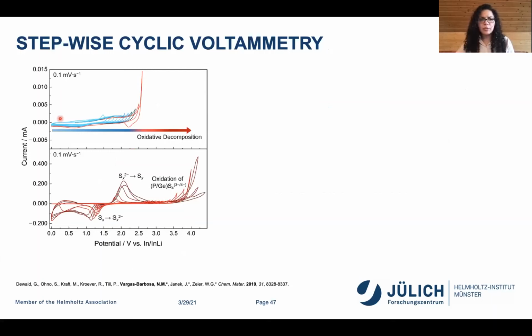The idea here was to start at OCP and then scan to a specific positive potential and then return, doing 2 cycles. If the 2 cycles were on top of one another, so reproducible, then you go on to the next one. This is how we were able to establish this color coding from blue to red, where already starting here, at about 2.3 volts versus indium lithium, we start observing degradation. This is just 1 cycle, but we actually measured 2. When they don't overlay, that was our cutoff. Okay, our material is starting to degrade.